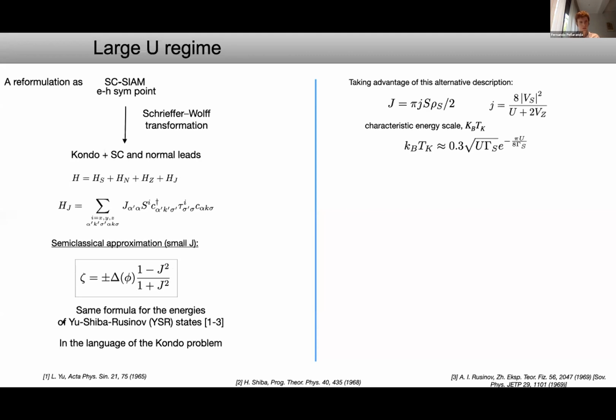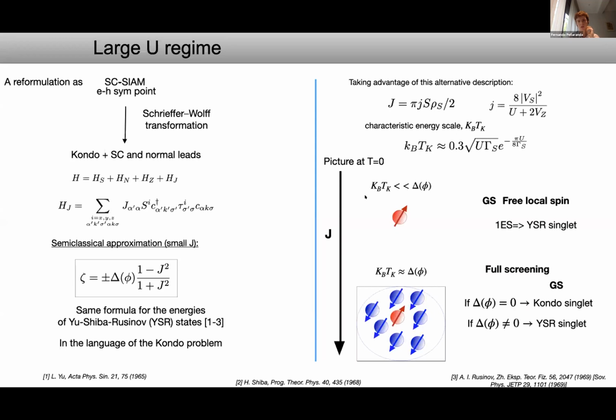This is the standard expression for the energies of Yu-Shiba-Rusinov states, now written in the language of the Kondo model. So, taking advantage of this alternative description, we can express J as a function of the Anderson model parameters, and we can also get an estimation of the Kondo temperature of the problem, at which it becomes non-perturbative in J. So the physical picture at zero temperature will be the following. When the Kondo temperature times Boltzmann constant is the lowest energy scale of the problem, the ground state is just a free local spin, and the first excitations are YSR singlets described by this expression.